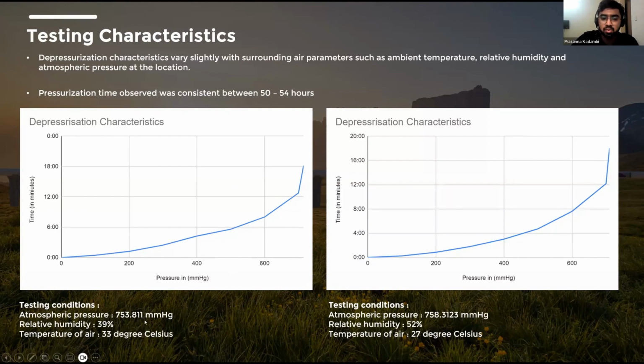One of the testing conditions is probably during the daytime. It's more during the afternoon hours, where the relative humidity is much lower because of the higher temperature of the air, and the atmospheric pressure is also kind of low at that point of time. So if you see the depressurization time it takes from 0 to reach a maximum vacuum pressure inside the tube of around 715 mmHg, which is roughly 94.5% vacuum held inside the tube. While traversing along this curve, if you look at the slope, there is not that kind of steep part wherein the depressurization curve is evolving.